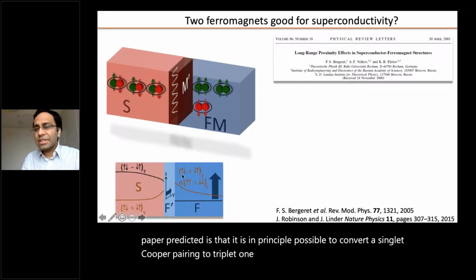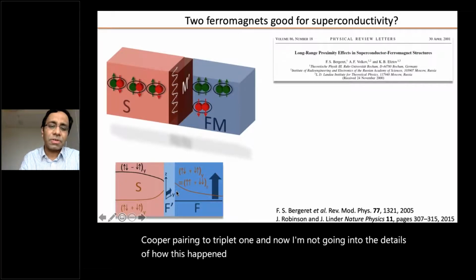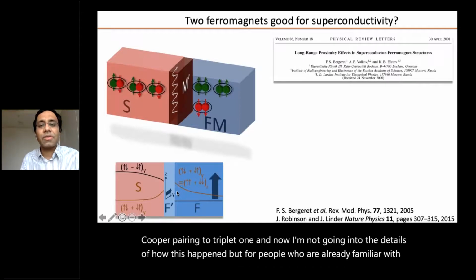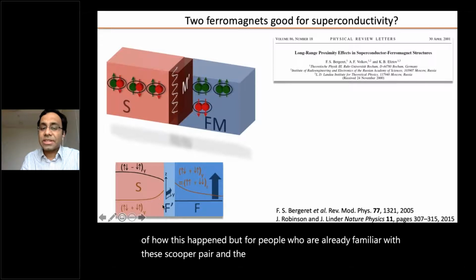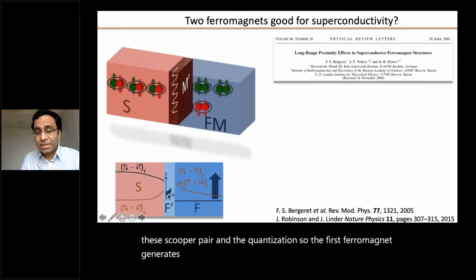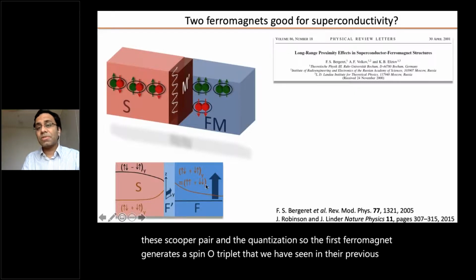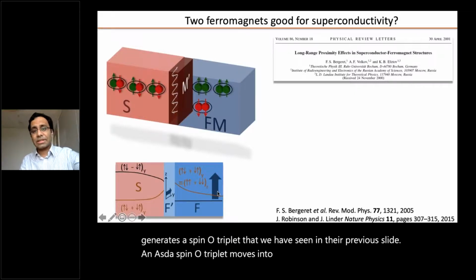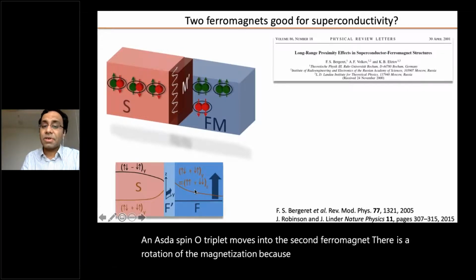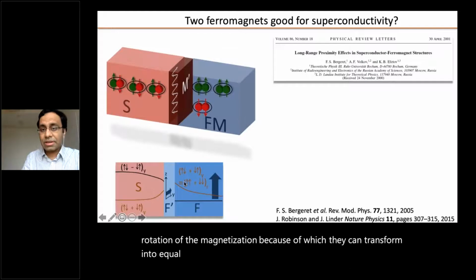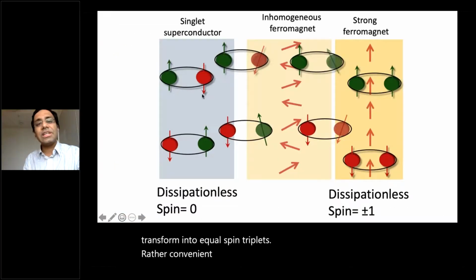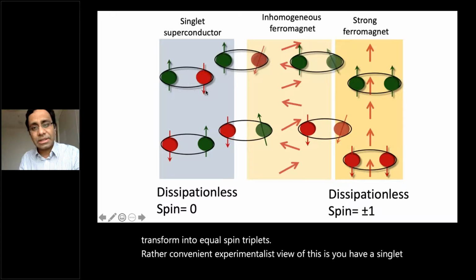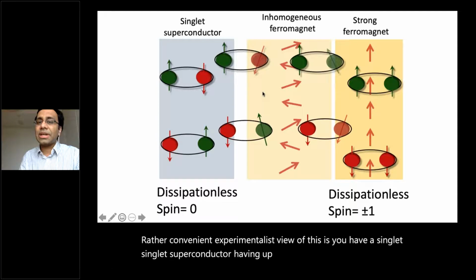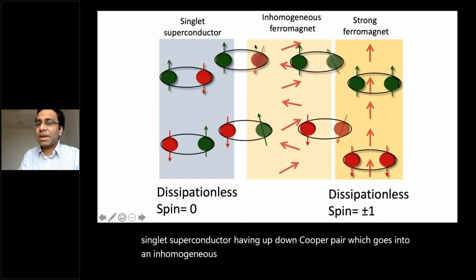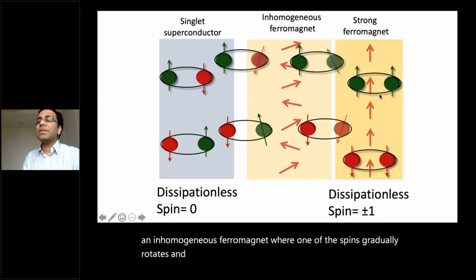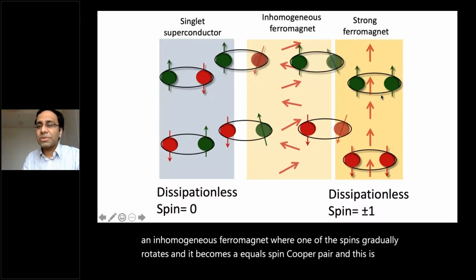I'm not going into the details of how this happened, but for people who are already familiar with this Cooper pair and the quantization, the first ferromagnet generates a spin-zero triplet that we have seen in the previous slide. And as the spin-zero triplet moves into the second ferromagnet, there is a rotation of the magnetization, because of which they can transform into equal spin triplets. A rather convenient experimentalist view of this is you have a singlet superconductor having up-down Cooper pair, which goes into an inhomogeneous ferromagnet where one of the spins gradually rotates and it becomes an equal spin Cooper pair. And this is what we plan to do.